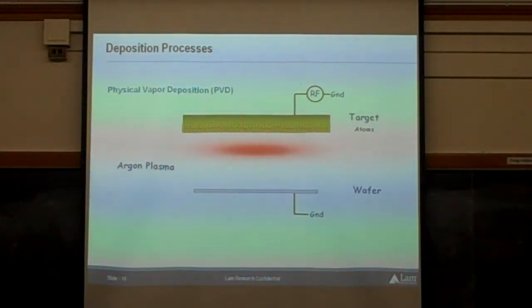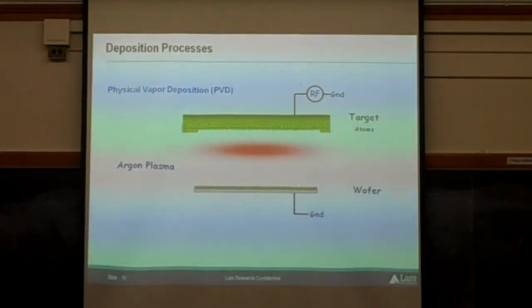They're in the gas, and I can accelerate them so they bombard this target. They sputter off an atom, and it's going to go line of sight, because it's low pressure, down to the wafer. And so I'm basically transferring a layer of metal from this target that I used onto the wafer. And it should look like this. Okay, so that's our physical vapor deposition. So it's just a physical process, right? I'm just sputtering, bombarding this target with little projectiles of ionized argon. And okay, here's copper, titanium, tantalum.